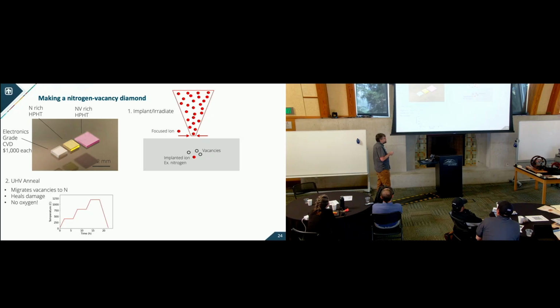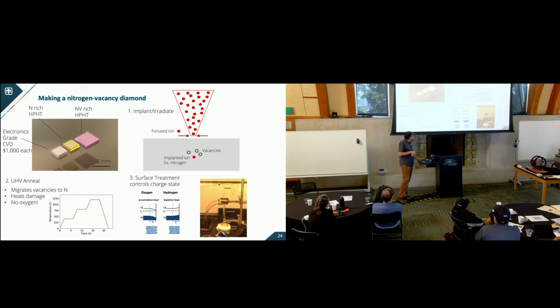And so we take it up to 1200 C. Now, I'll talk about this more later, diamond is actually metastable, right? It's made in high pressure, high temperature. So you can't damage it too much and still anneal out that damage, because it's more happy being more graphite-like in ambient conditions. And then we do surface treatment to control the charge state.